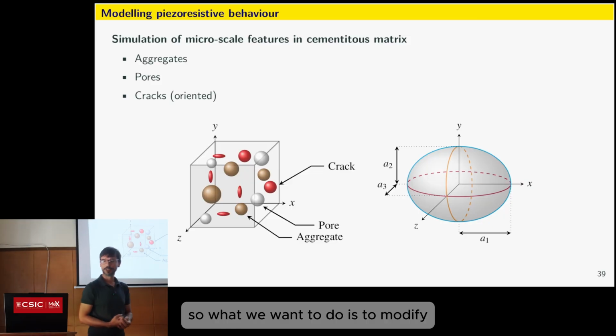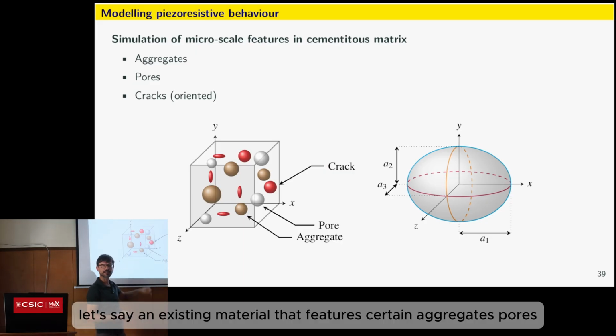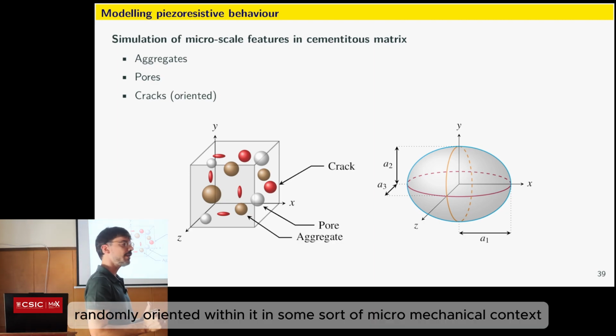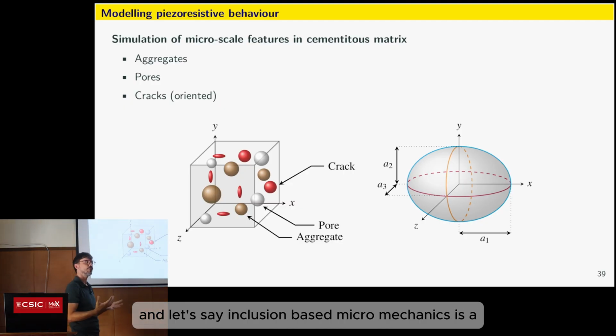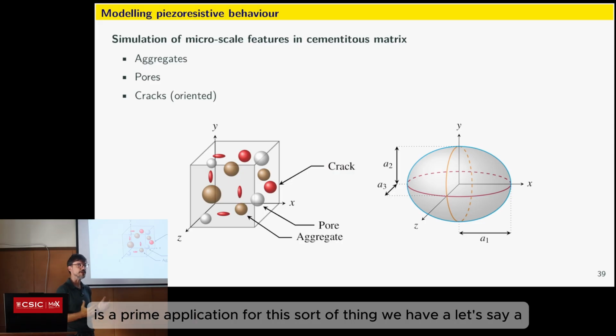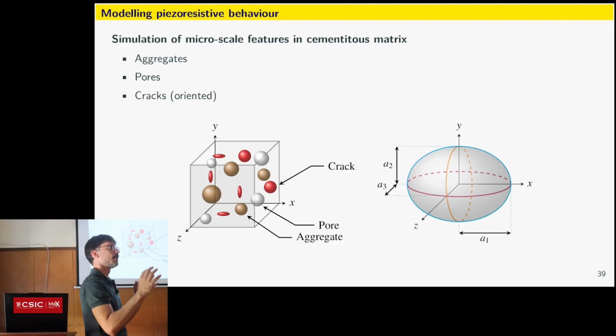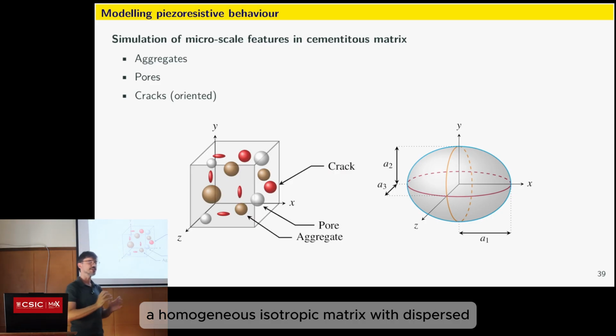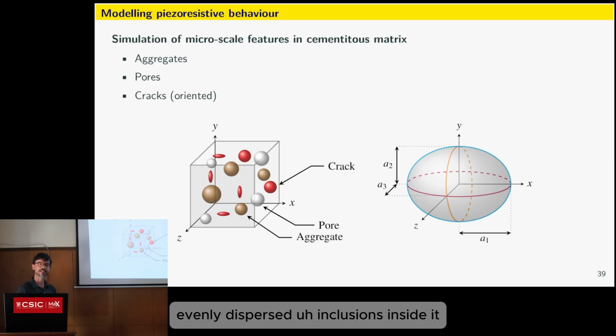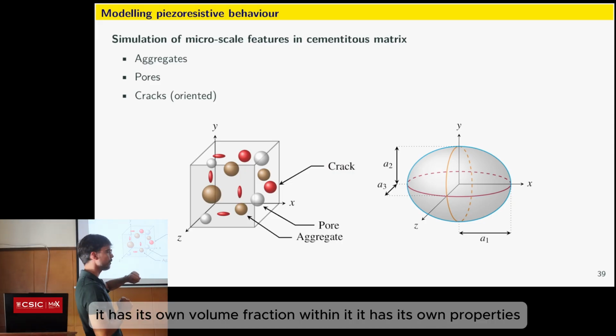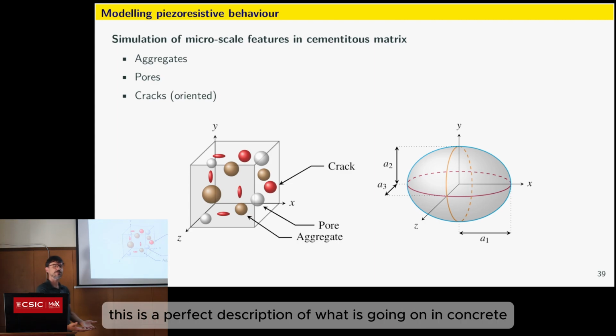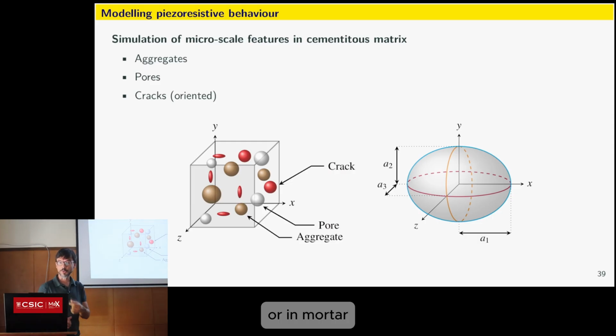So what we want to do is to modify an existing material that features certain aggregates, pores, and cracks randomly oriented within it in some sort of micromechanical context. Inclusion-based micromechanics is a prime application for this sort of thing. We have a homogeneous isotropic matrix with evenly dispersed inclusions inside it. Each one has its own aspect ratio, its own volume fraction, its own properties. This is a perfect description of what is going on in concrete or in mortar.